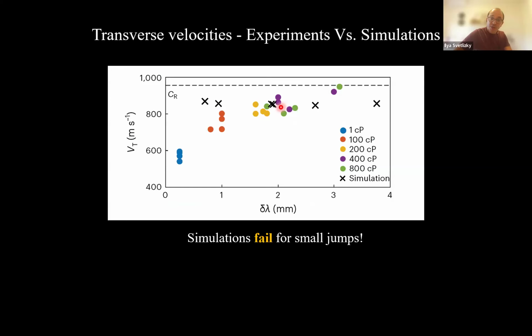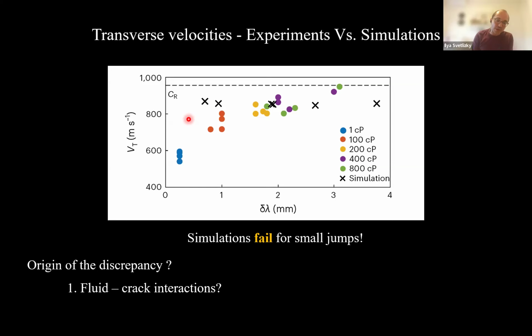Interestingly, the simulations fail to describe the really, really small jump amplitude. So as the jump amplitude increases, it works well. At smaller values, it fails. So we don't have an answer. I will give you two options. So what is the origin of this discrepancy? Why doesn't the brittle theory work very well at very small amplitude? One naive answer would be, well, you neglected the motion of the fluid. Maybe when the fluid is very close to the crack, some weird interaction between the two slows down the crack dynamics. I don't know how to rule out this option.